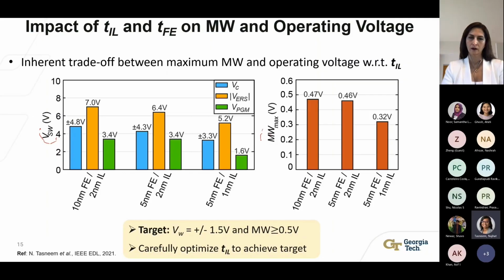The results of this experiment were summarized using this bar chart, which indicates the variation of the write voltage and the maximum memory window with respect to the ferroelectric layer thickness and the IL thickness. This bar chart indicates that the operating voltage, however we define it, decreases as we decrease the interfacial layer thickness. However, at the same time, the memory window also decreases if the interfacial layer thickness is decreased. So there is an inherent trade-off between the maximum memory window and operating voltage with respect to the interfacial layer thickness. If we want to achieve our target for embedded application, we need to carefully optimize the interfacial layer thickness, keeping in mind the trade-off between the memory window and the write voltage.